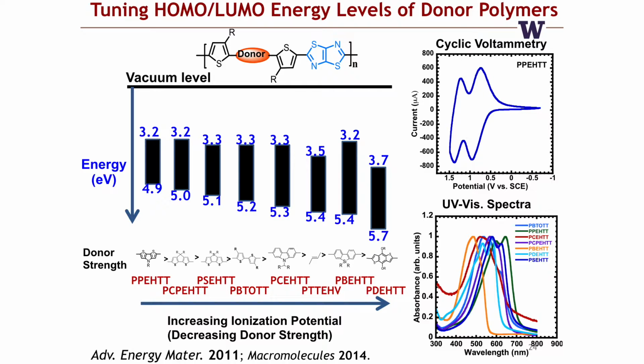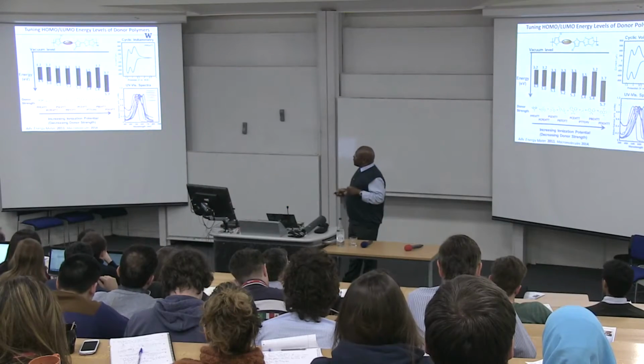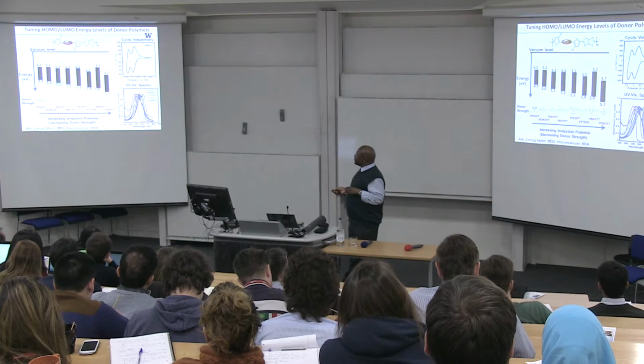All right, so what I show here, we're not going into the details of the chemistry of making these polymers, but the basic structure is shown here. What we were particularly interested in was to tune energy levels and therefore the band gap and therefore the absorption characteristics. And what you can see is that we have the LUMO relatively fixed while varying the HOMO over quite some range. And what we hope to be able to do with this, and what we have done, is to, from this library of materials that we have generated, select groups of these materials to try and extract structure property relationships from such a cluster of materials.